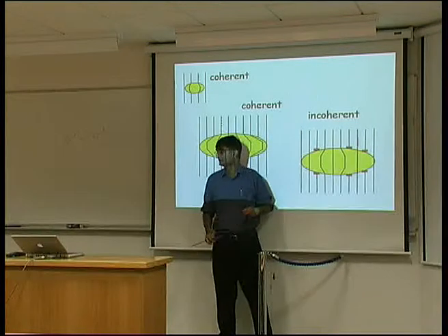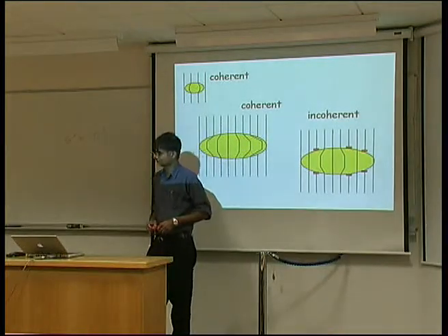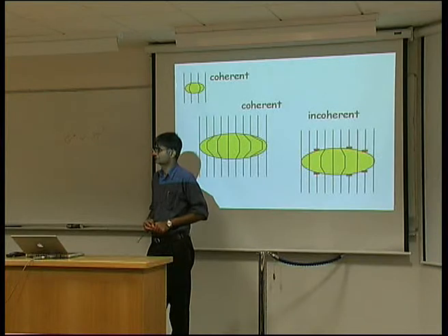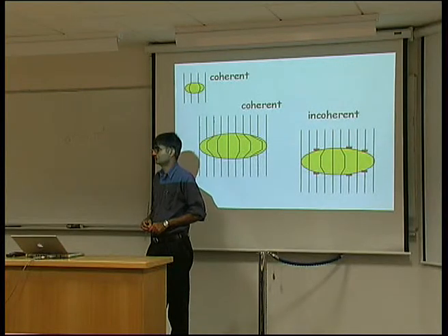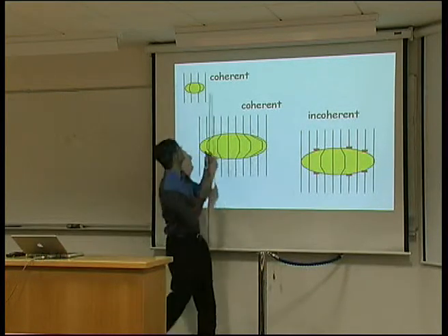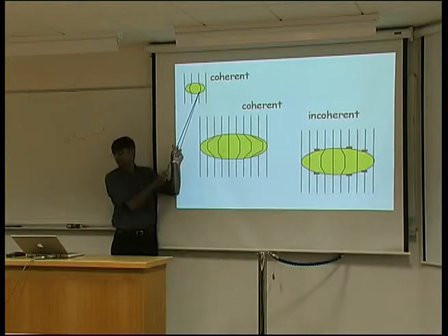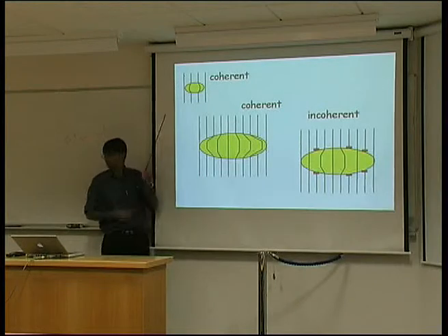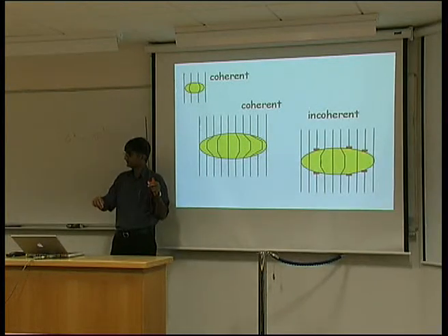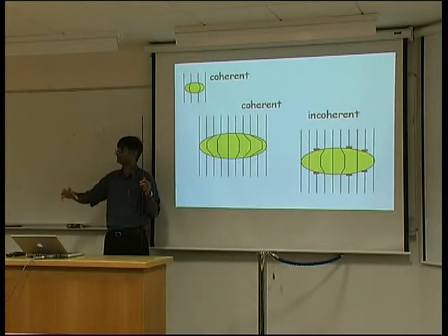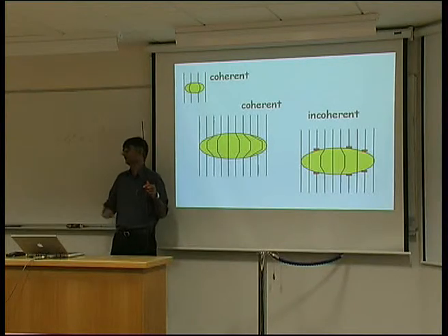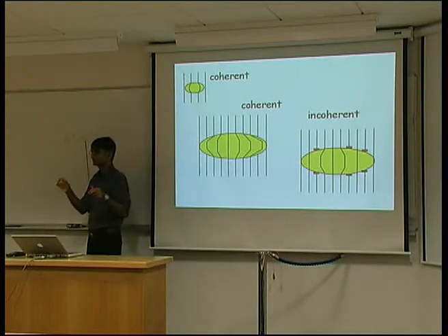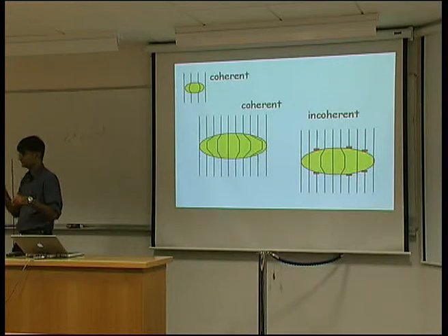So if you have two different precipitates where the particle is the same size, it's just dependent on the actual structure, whether those planes are preserved as coherent or not. You see, if this spacing here is greater for one phase than another, then breakdown of coherency happens earlier, at a smaller particle size. So that's the structural component of interfacial energy.